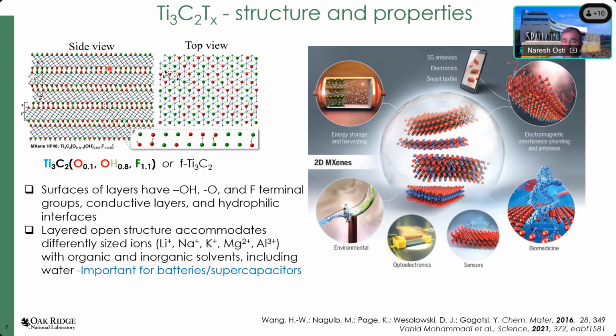The properties of MXenes come from the surface terminating groups. In the example where we have used neutron total scattering together with multimodal computer simulation, we showed that the MXene surface is rich with oxygen, hydroxyl groups, and fluoride groups. Because of these surface terminal groups, this gives hydrophilicity to the MXene structure, and MXene is conductive by itself. This is a unique combination of conductivity and hydrophilicity within a material, which can rarely be found. Because of this, MXenes allow intercalation of different types of metal ions, together with solvent, water or organic solvents or ionic liquid, in between the layers. Therefore, MXenes have shown promising behavior to be used in different types of applications, which you can see here.